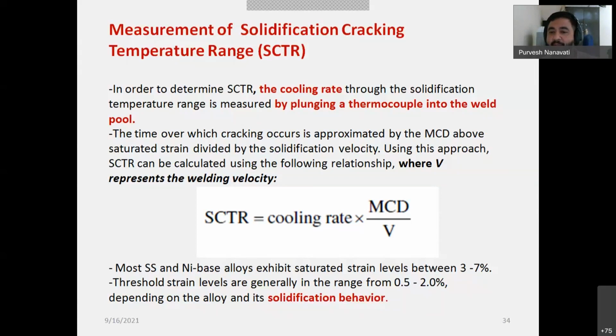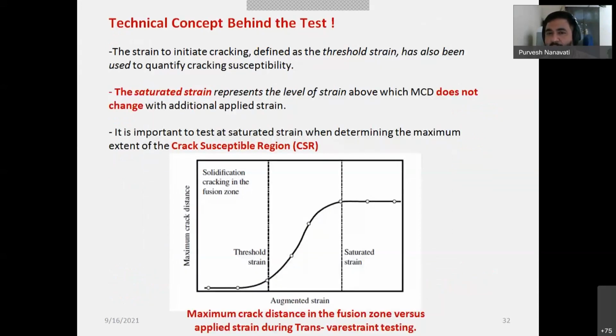So for stainless steel and nickel based alloy, the saturated strain levels generally range from 3 to 7%, and threshold strains range from 0.5 to 2%. It means you require 0.5 to 2% of minimum strain to develop the crack, and your sample made of stainless steel and nickel based alloy will show a saturated strain level. It means the maximum crack distance will become constant after, say, 7% strain level, as per the previous slide, right? I hope everyone understands this, right?